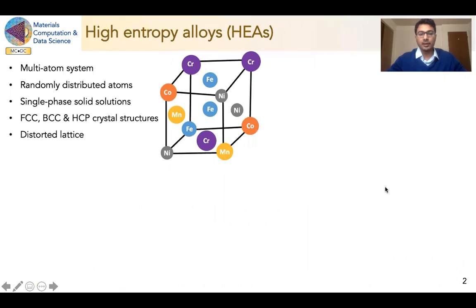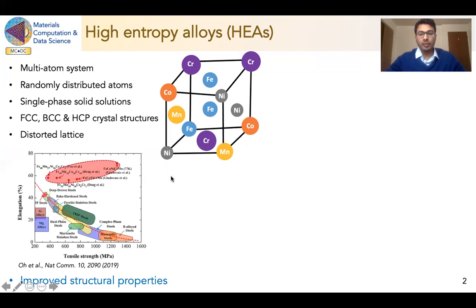High entropy alloys consist of multiple principal elements which are placed randomly in a crystal structure, as you can see in this cartoon figure. These alloys normally have FCC, BCC, and HCP crystal structures with distorted lattice. Very good mechanical properties have been observed in these alloys, as shown in this bottom figure. The vertical axis is the ductility, and the horizontal axis is the strength. Conventional alloys are lying on this dotted line, showing that there's a trade off between both these properties, meaning when ductility is high, strength is low, and vice versa.